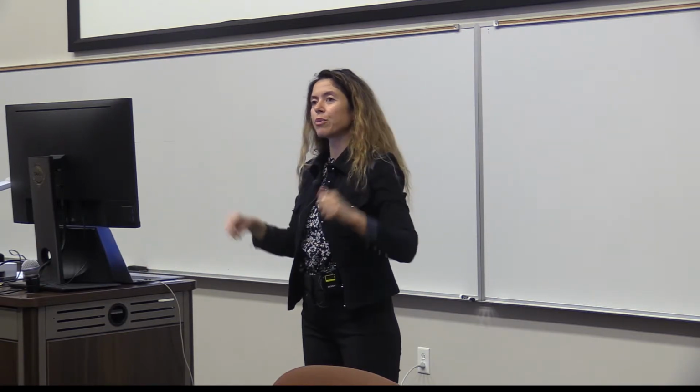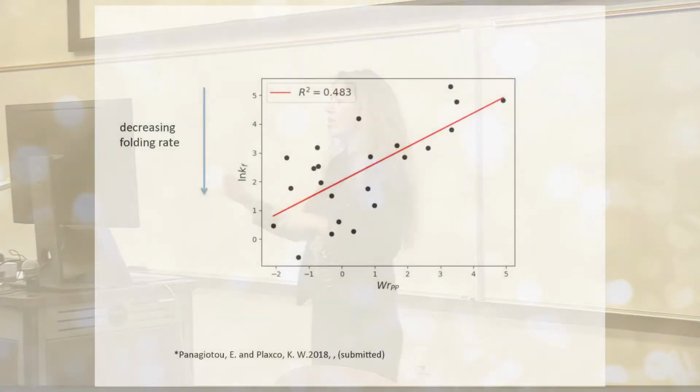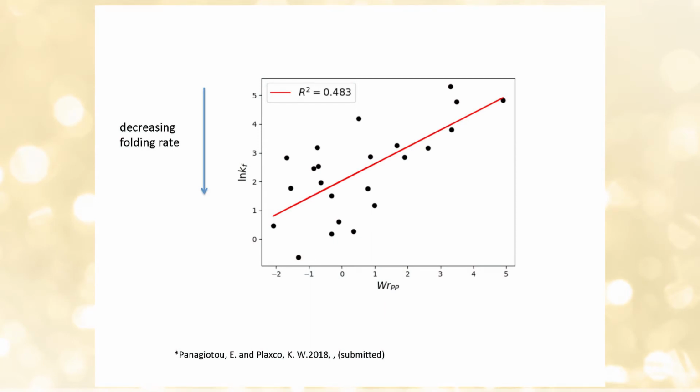And then we provide, and we can discuss why this is the case, the width of what we'll call again the primitive path, the backbone, without taking into account helices and strands, to be the width of the protein minus the width of the helices and the width of the strands. And just that, which is a very simple measure of entanglement, shows a correlation which, for that type of data, is strong.